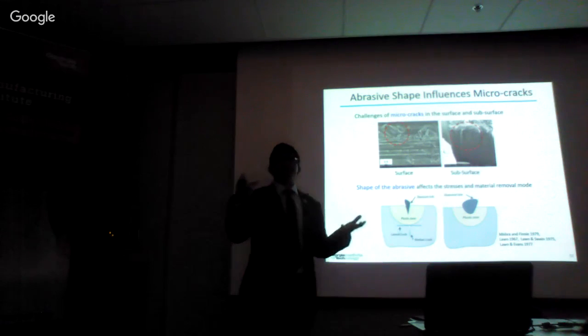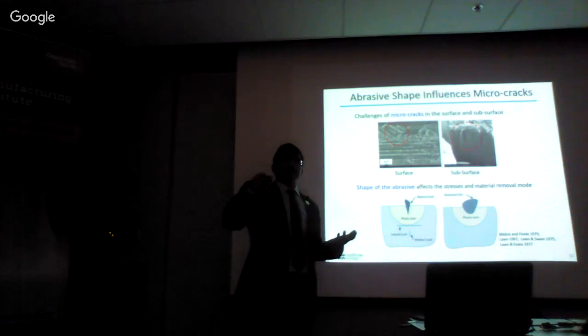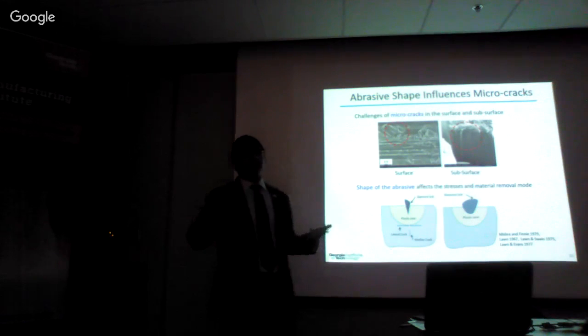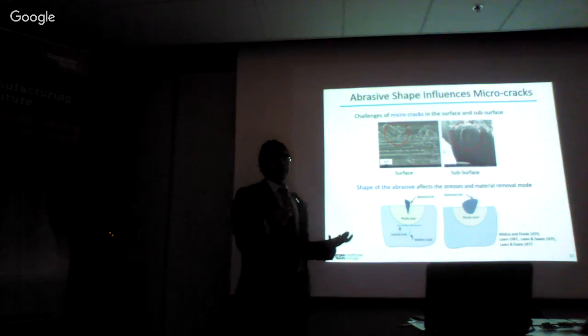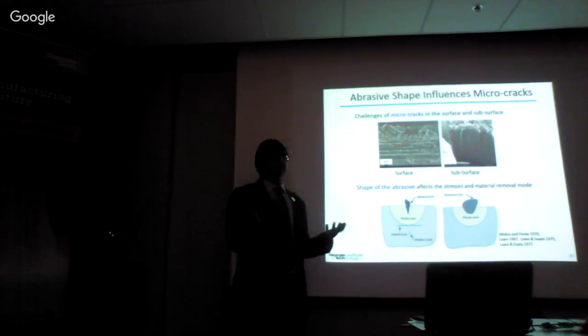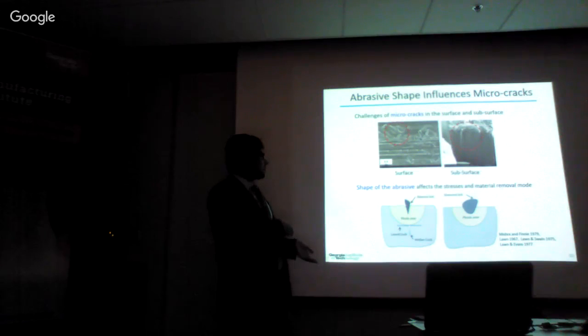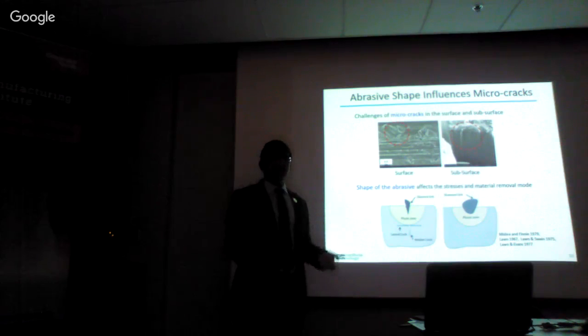And the cutting tool here are the diamond abrasives of different shapes and sizes. We see from prior literature in indentation experiments or scribing with idealized shape indenters on brittle materials like glass, silica, and even silicon, that the different shape of the indenter would affect the stresses created below the indenter in the material differently. If it's a sharp-shaped indenter, there'll be a plastic zone near the contact region, and then there'll be a median crack and lateral crack formed during loading and unloading of the indenter.